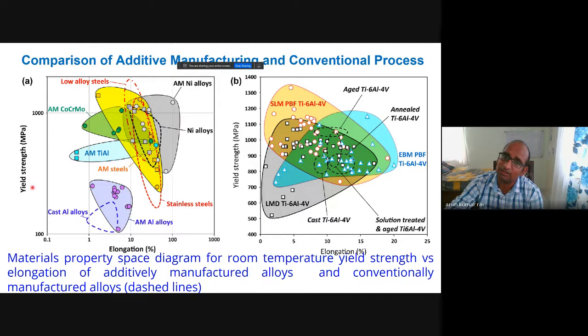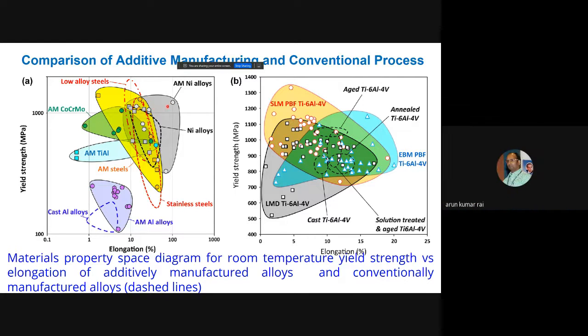Similarly, you take titanium aluminum alloy. In titanium aluminum alloy also you will see with additive manufacturing, some reports show it has a good yield strength but poor ductility. But there are certain processes you can see here where they have got good ductility as well as better strength. Similarly, you take nickel alloys, low alloy steel, cobalt, chromium, moly alloys. You will see that this dotted line is actually conventional and solid line is additive manufacturing. In the case of nickel alloys, people have achieved better strength and better ductility than conventional process by optimizing process parameters and other things. So additive manufacturing is progressing nicely and it may take over in future.